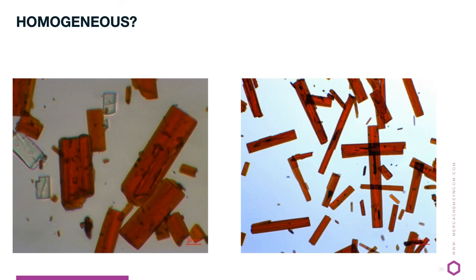Having a ranking does not necessarily give you the best results. So, when you look to the left, the microscopy picture here shows only a few transparent impurities. These were not detected by any of the other analytics and only visible by microscopy. So don't use only the numbers that you get from your equipment, but also have a look for yourself what actually is the form you're making.